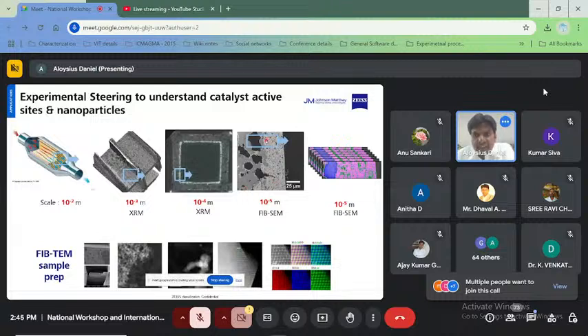And then further, it was taken for sample preparation to be put under the TEM. So you can see here the sample has been prepared and put under the TEM. They wanted to understand the distribution and the locations of the cerium and zirconia rich areas, because those are the areas where they predominantly try to hold the catalytic material. So that's exactly what they did. It is a low density material, and they also wanted to do electron energy loss spectroscopy, to understand the remnant of the catalytic particle.